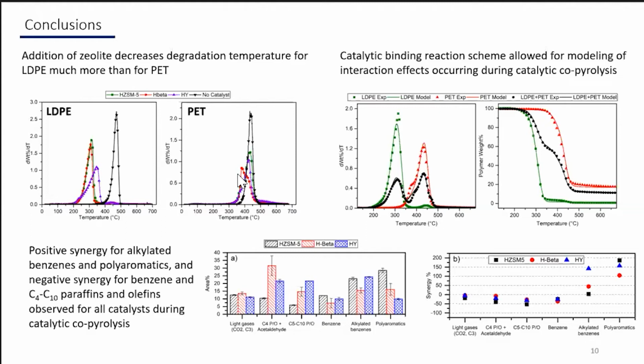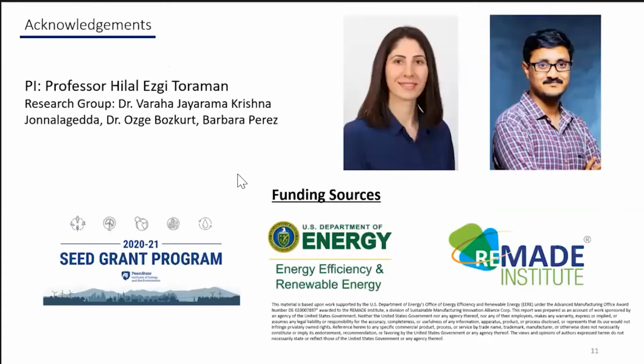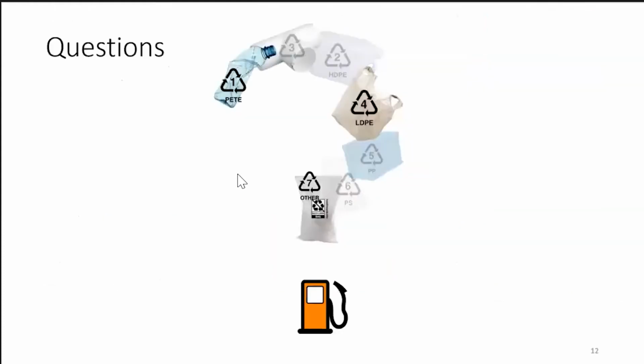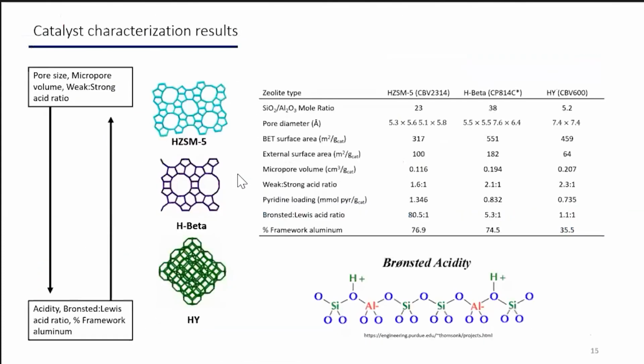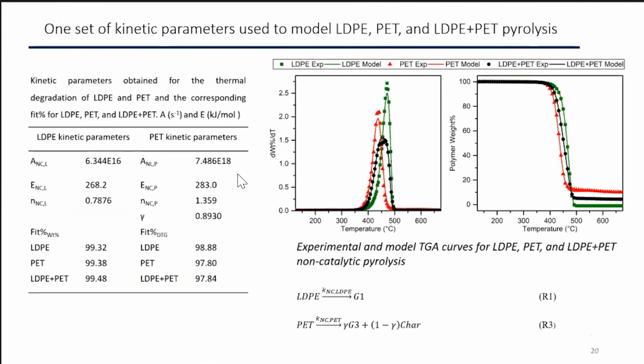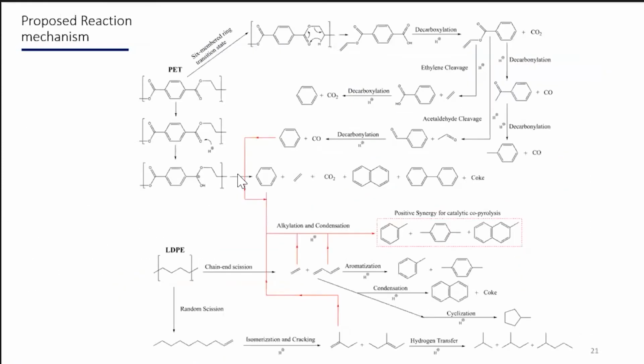So I believe that what may be happening, I think there should be a slide for this paper where we had a proposed reaction mechanism. So what we believe is happening is that there is this proton, and that it may be attacking this oxygen in this PET polymer, and that's what leads to this enhanced degradation.